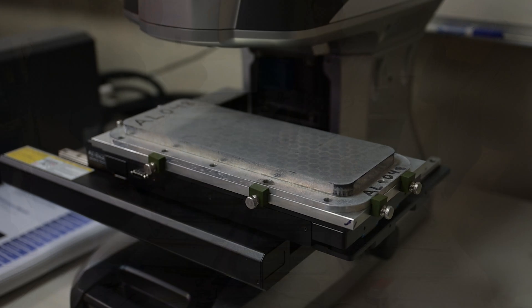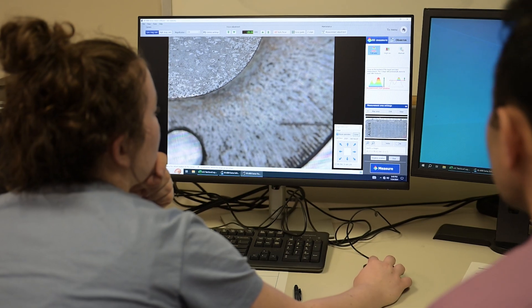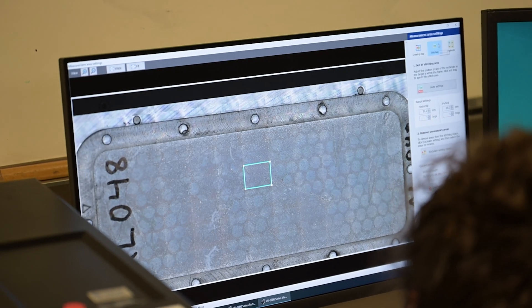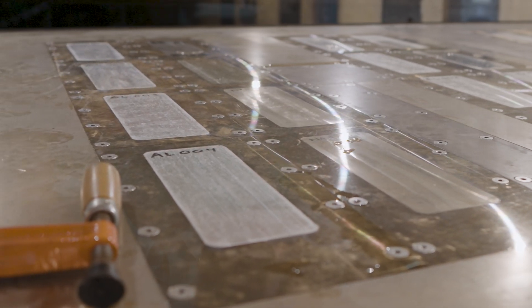The reason we put it in all the locations is because we want to verify that we're getting uniform distribution across the span of the foil. The foil is 10 feet wide and we have slots for seven different spanwise locations. Because we're testing all these materials at the same time in different locations, the way we wanted to start out was by showing that all the locations are about the same — and we did discover that. So we're very happy about that.